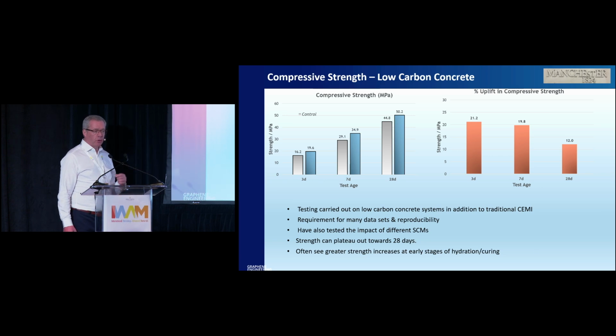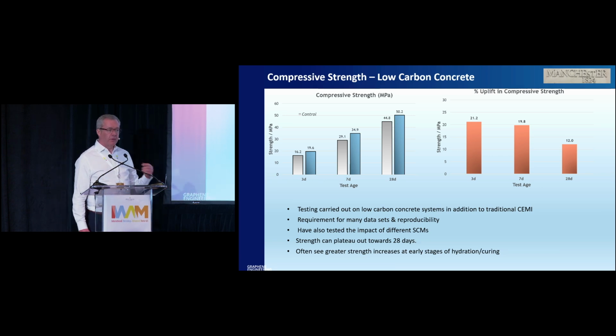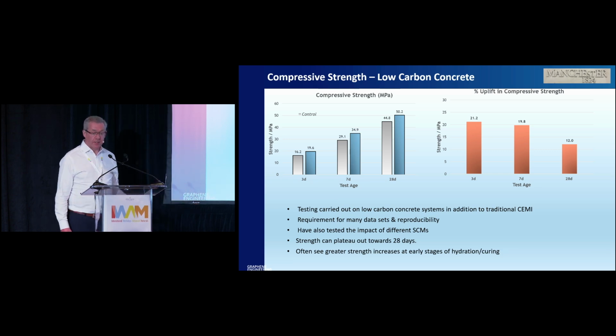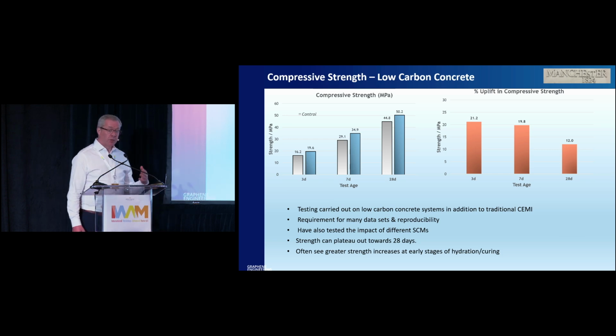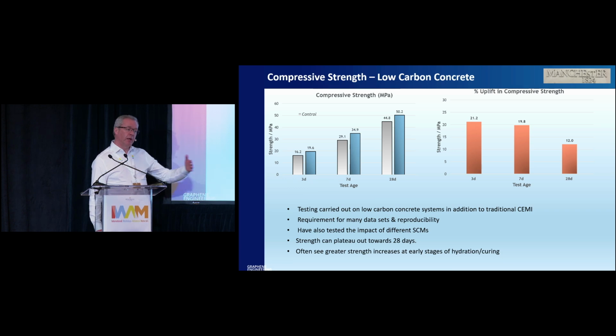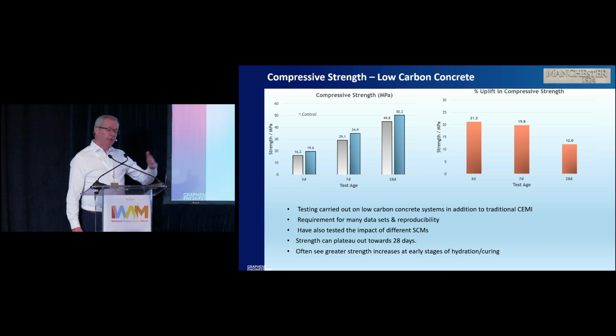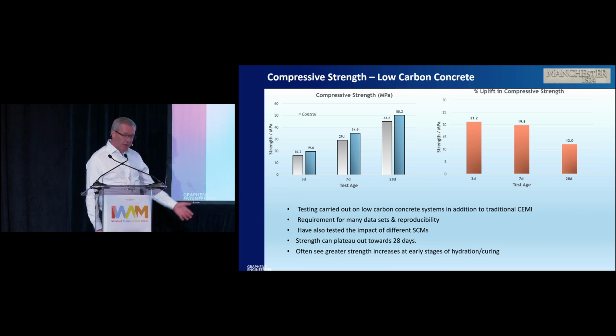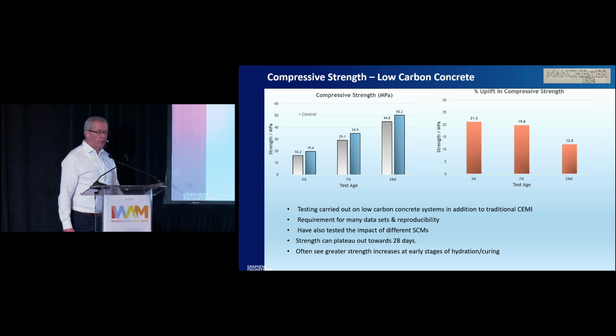Now, if you start to look at the value, good quality graphene is about £1,000 per kilo, but the loadings per ton are about 0.05%. So very, very low loadings, and the cost per ton of graphene is quite low. If you take the 7-day trial on a precast, you can start to use that precast and transport it, rather than waiting 28 days. So the value graphene brings is not just in the performance of the material, but in the usability of the material as well.